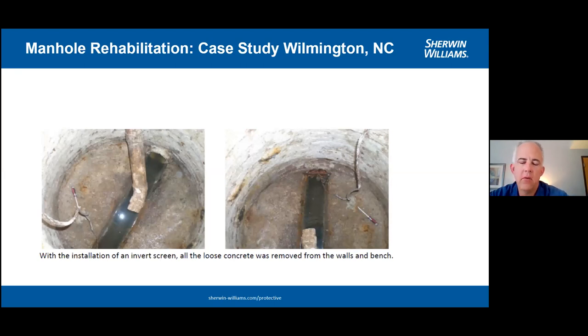The pH on this concrete when we started was about a 7. Once we pressure washed it and removed all the contaminated concrete, we got up to a pH of about 10. 9 to 10 is what you want to see before you start doing rehabilitation on your existing concrete structures. If your pH shows, using a simple pH pencil, below a pH of 9 or 10, that means you still have contaminated concrete and you need to keep removing further until you get to that higher pH.